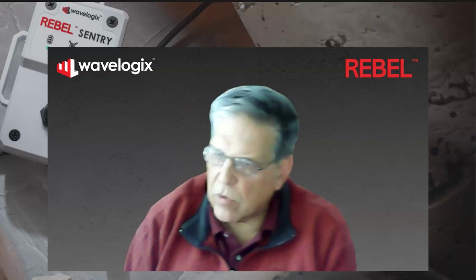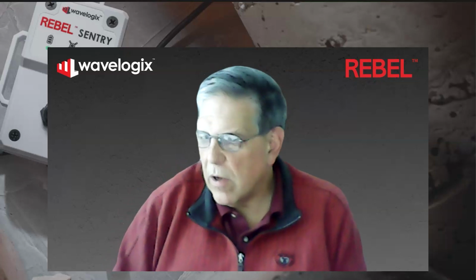The Rebel system is agnostic to all of that because we're looking at the actual strength or structure or stiffness of the material. And the stiffness of the material is dictated by the type of aggregate. So if you change the aggregate from limestone to granite, you're going to be changing the ultimate stiffness or strength of that mix, and we're going to pick that up in the sensor. The resonant frequency is going to be different for limestone than it is for granite, and we will deliver a different strength, and that strength will be comparable to the type of aggregate that's used.